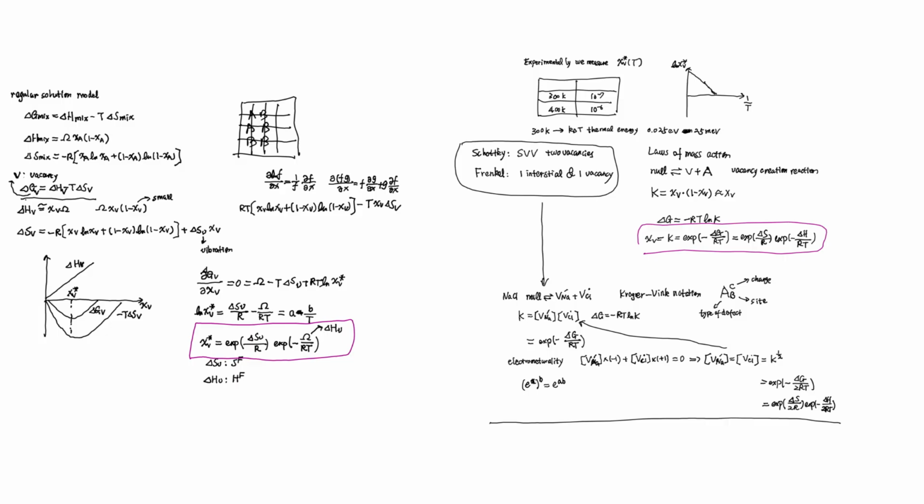So you're saying this is a linear equation as A minus B over T. Yes. So we plot natural log XV as a function of 1/T. Because the equation is saying ln XV against 1/T is a linear equation, so A minus BX, it's going to look like this.